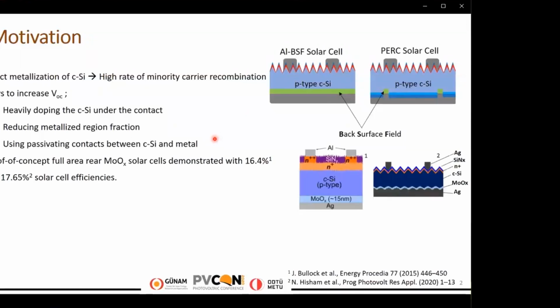Recently, P-type solar cells utilizing only the third way for VOC increase, featuring full area molybdenum oxide hole selective rear contacts, have been demonstrated with efficiencies of 16.4 and 17.65%, as Dr. Nasser mentioned in the morning session today. And these direct metal molybdenum oxide contact structures are still limited by VOC and JSC factors.